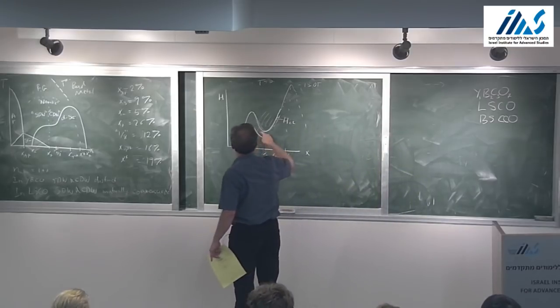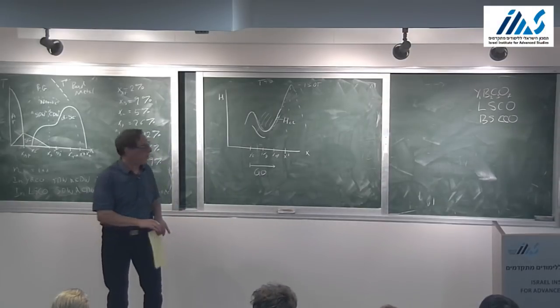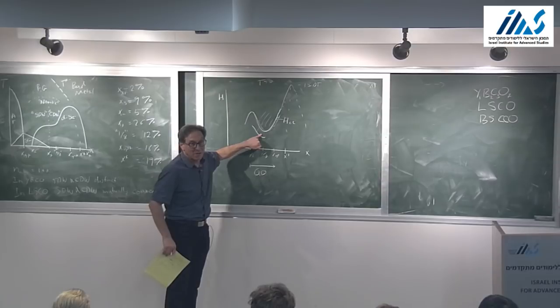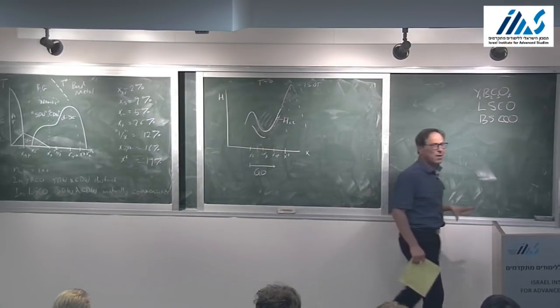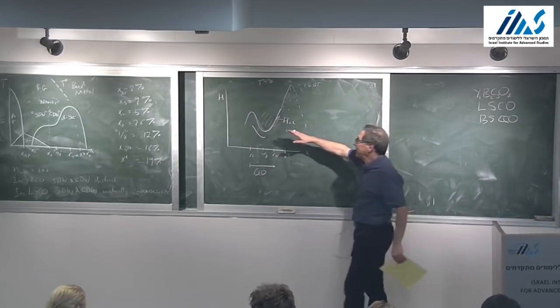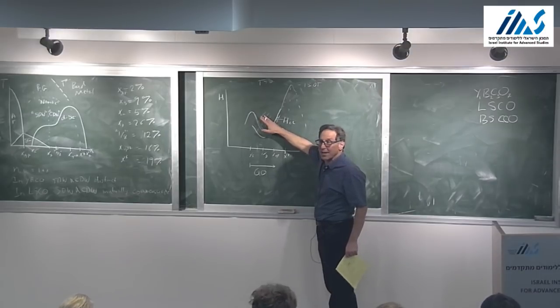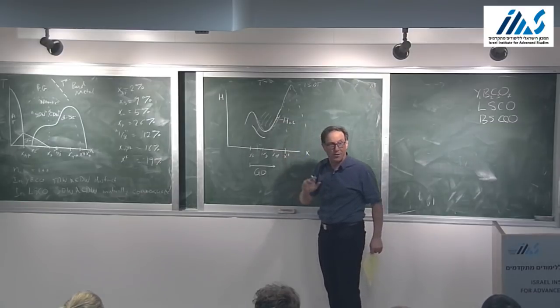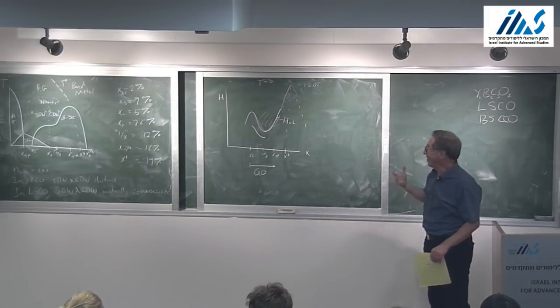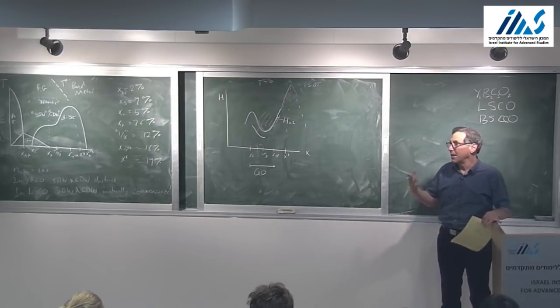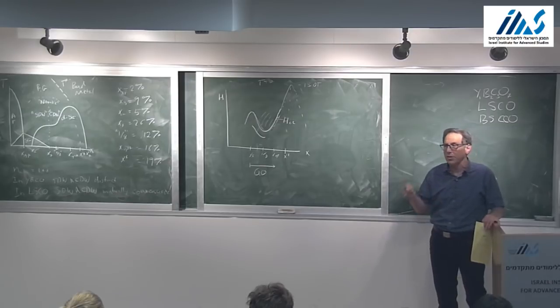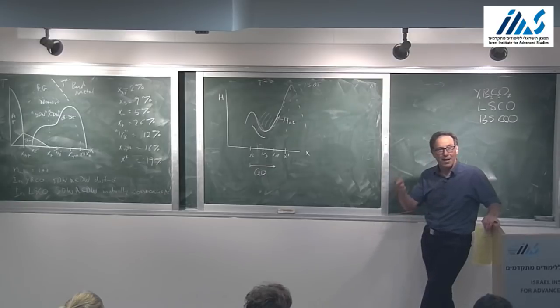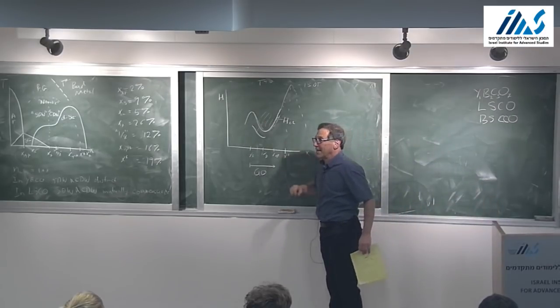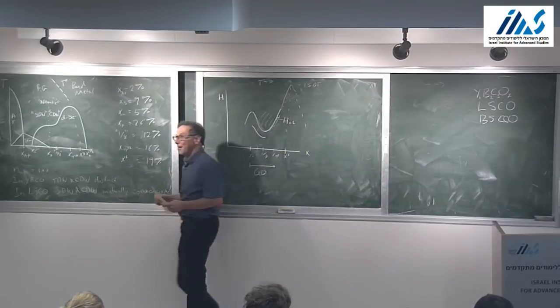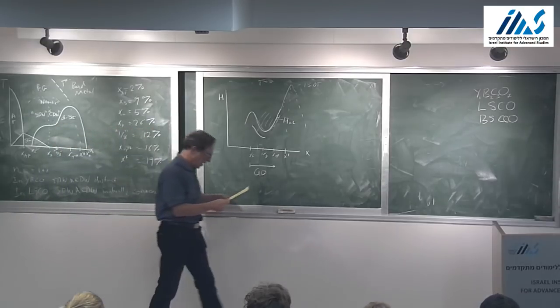The quantum oscillations are seen, actually, sometimes in some features they're seen down to as low as this line, which I'm about to draw. I mean, not in resistance, but in magnetization. But this normal state does exhibit some features of superconductivity, some rather dramatic features of superconductivity. And I think the only way that one can understand that is if one imagines that these cleanest and best of all crystals in the universe are macroscopically inhomogeneous, and that small portions of the system that are nonetheless large compared to the penetration depth are still superconducting at these high fields. At least I don't know any other way of explaining that. That's an extremely unpopular explanation.